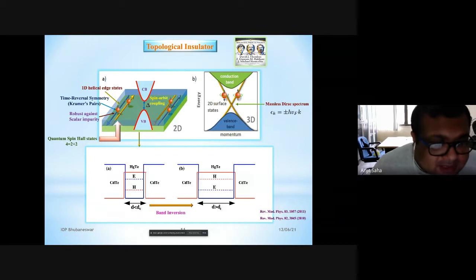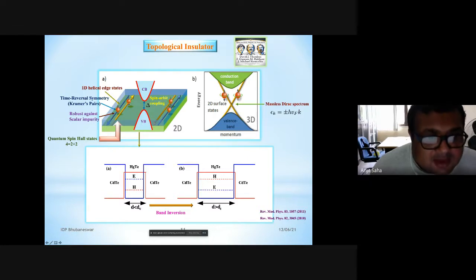Also, another feature is that if you think this state has up spin with left moving, down spin with right moving, so the total charge conductivity for this system will be 0, because up and down are propagating in opposite directions with equal amplitude. So now what will happen if you measure the Hall conductivity, then you will get a complete spin Hall conductivity here. It's pure spin Hall conductivity, no charge. So for that reason, these states are called quantum spin Hall state or quantum spin Hall insulator. So there are many names of that.